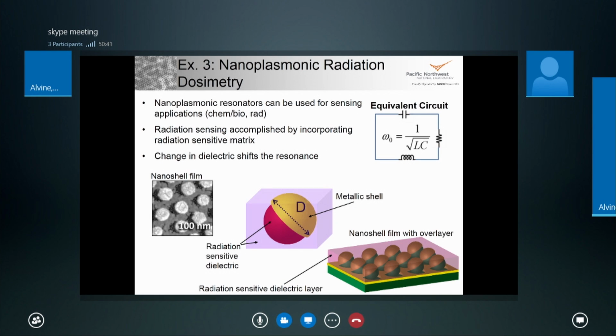Other things we've been able to do with these structures is look at using them for sensing. What we were primarily interested in was using them for radiation sensing. Because the nanoshell is essentially a resonance cavity, if you change the properties of the material inside the shell, or right next to it—say you have an overlayer of material that's sensitive to radiation—if you damage that material and change its index of refraction, then you can get a shift in that resonance. Essentially it's like changing the capacitance of a cell, and you see a shift in the resonance of the LC circuit because you've shifted that capacitance value.